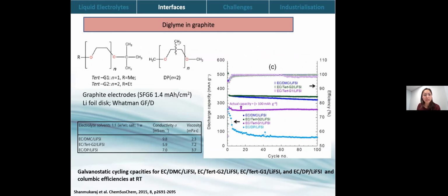However, if we change the structure of the diglyme, in this paper, they show two different types of glyme. So either we can have a monoglyme or a diglyme, and then the R group on the left can be a methyl group or an ethyl group. And so when the glyme is branched, here we can see on the right, it's a branched molecule as compared to being linear. They are considered also as hindered glymes. In this paper, they call it hindered glymes. And when these hindered glymes are used, we can see here on the figure on the right that the discharge capacity actually improves. And by changing the structure, we prevent the co-intercalation of the glyme into the graphite structures.